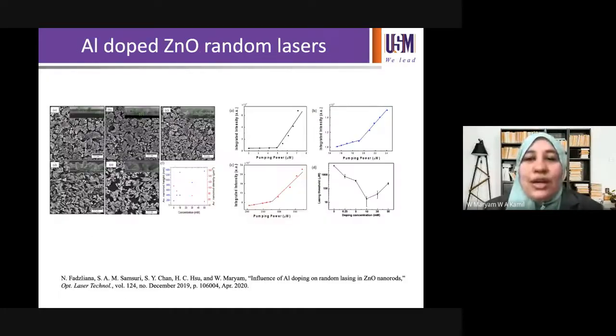And to reduce the threshold further, we decided, okay, let's dope the random laser. Doping has been shown for semiconductors to reduce the threshold for lasers. So we decided to try and dope with aluminium. That's the simplest doping, the most proven doping in chemical bath deposition. That's why we chose aluminium. There is a bunch of metals we can choose from actually. We were hoping for some plasmonic effects to occur, but we didn't see that.